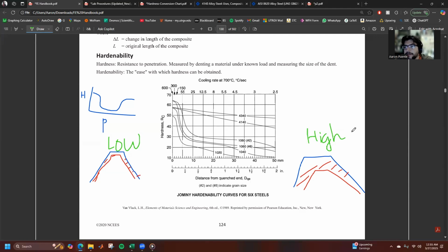Something with machine elements and you see stress below the surface. But yeah, the idea is you want hard and then a quick drop off. Because if we were to say we need 40 HRC, the alloy steels, look at this, up to almost 2 inches. 2 inches of a case depth is way more than you need versus something like a 1020 forms this case that we see here with a nice quick drop off.